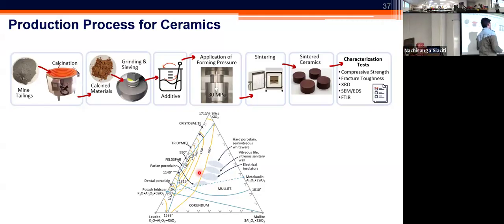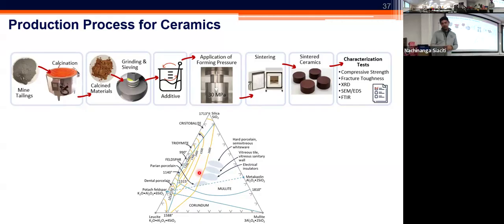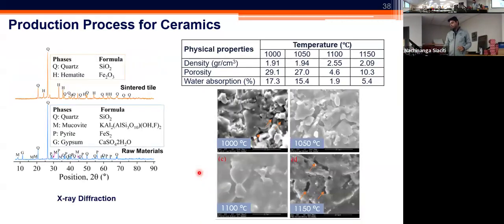So all you may need to do is to further grind it as needed, and then remove some of the barriers like the sulfate content, and then proceed with the grinding and addition of the lubricants, application of the forming to come up with your green ceramic to then go into a sintering oven, and then eventually you will have your sintered ceramics. And you can proceed with evaluation of different characteristics for these materials. So that's exactly what we did.